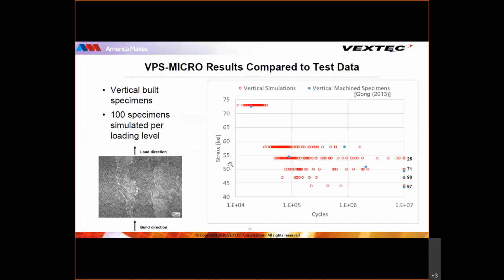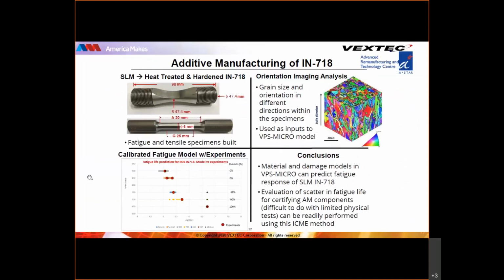So we also wanted to touch on some of the other things that we've been doing in AEM. Here you see some collaborative work that we've done with A-STAR, which is an advanced manufacturing consortium in Singapore, on selective laser melted IN 718. The volume element that's on the upper right-hand side of the image here is showing how the microstructure varies in different directions due to the SLM process. Specifically here showing the grain size and orientation. And these probabilistic values are direct inputs for the VPS-MICRO ICME type of modeling.